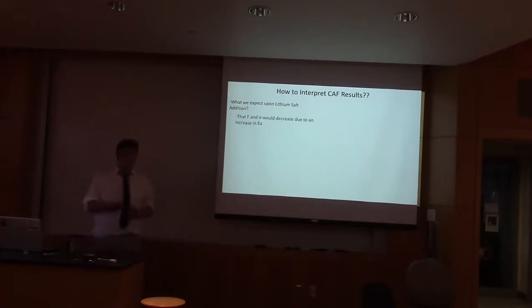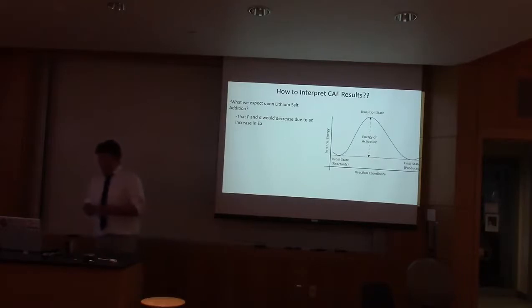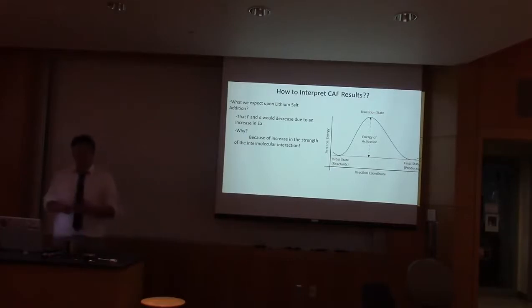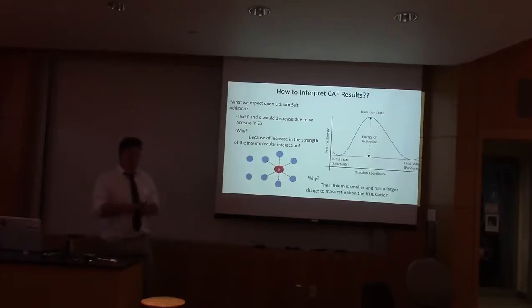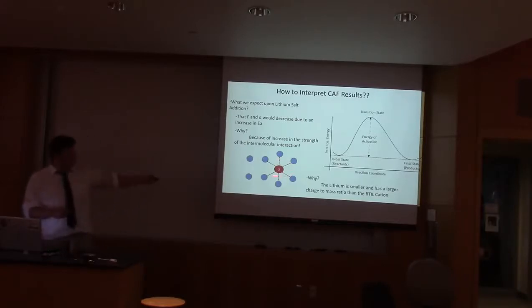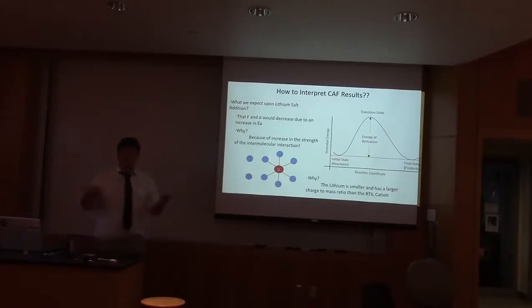Upon lithium addition, we expected that the activation energy was going to increase. If you remember this image from earlier, basically we were saying that it would take more energy to surmount to get into the transition state. Why? Because we expected the strength of the intermolecular interactions upon the addition of lithium for our liquid to also increase, because lithium is a very small and very charged ion. Therefore, its intermolecular interactions would be more likely to be significantly stronger than our big, bulky, room temperature ionic liquid cation.